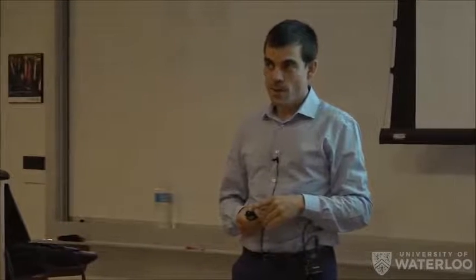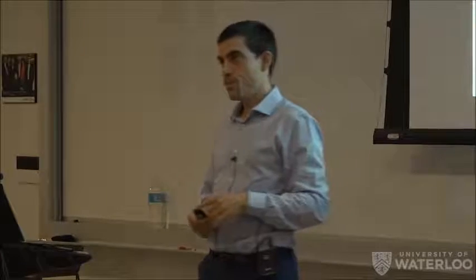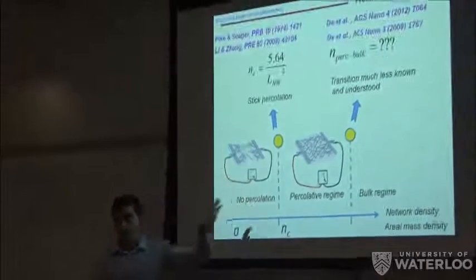And how about changing the conductivity of the nanowires? Because they are metallic nanowires, and you are coating them with zinc oxide. Zinc oxide is not as conductive as the nanowires. But you coat them once they have been deposited, where you have the contacts on, so the electrical connection is already made. So you coat the network, not the nanowires.